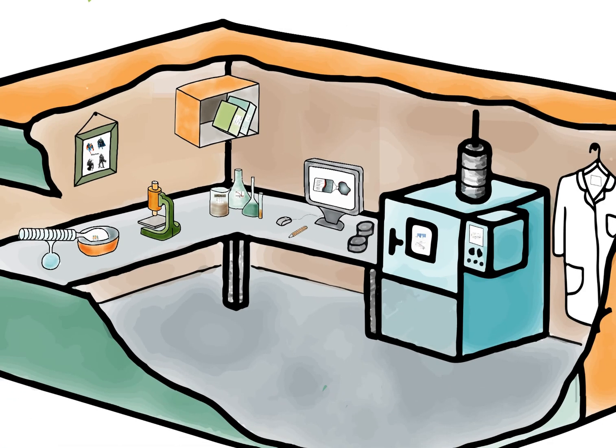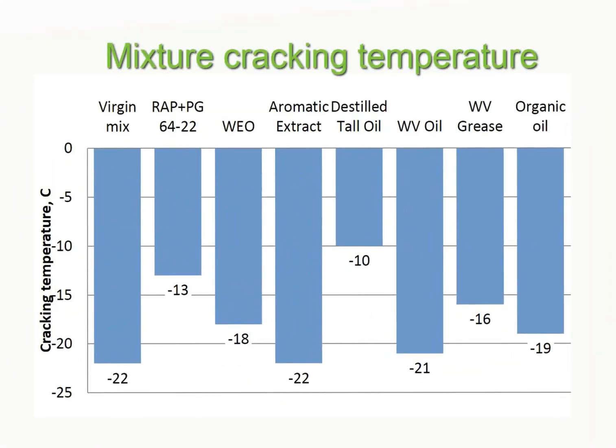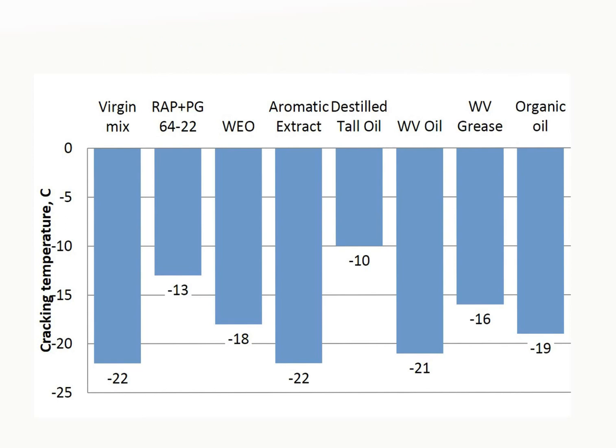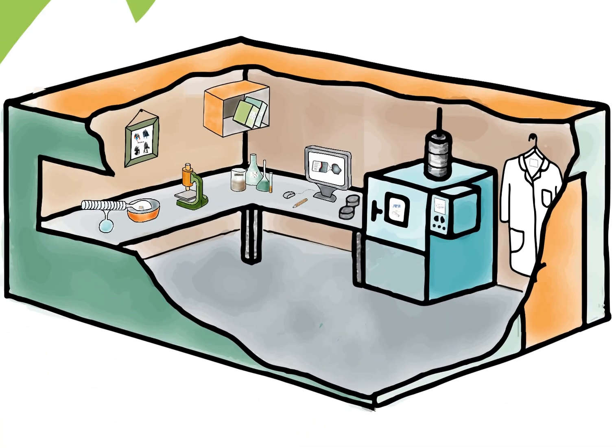After we saw that the concept of 100% recycling works, we wanted to go further and perform a thorough investigation of asphalt binder and 100% recycled mixture using performance-related test methods. The study demonstrated that at 12% dosage, rejuvenators provided the required rutting resistance, and most of the six tested products significantly improved low temperature thermal cracking resistance of both mixture and binder. Workability was improved compared to RAP, but remained lower than that of virgin mixture. Some rejuvenators slightly reduced moisture and binder aging resistance. Generally, at the 12% dosage, organic products outperformed the petroleum additives in most of the tested properties.